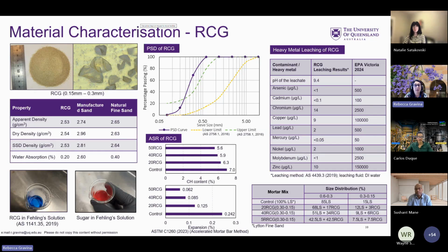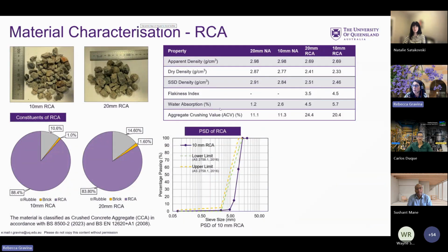In terms of the recycled crushed aggregates, the first thing we looked at was what are the constituents of those recycled crushed aggregates. We are very interested in the aggregate crushing value, because if the aggregate is too soft, then it's going to really impact the mechanical performance that we will achieve.